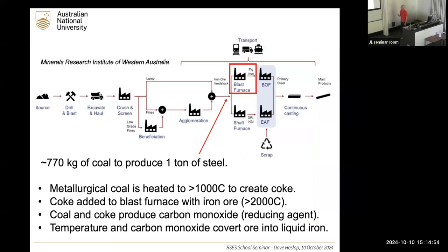So let's look at what's happening in this blast furnace. So, like I said, we've got blast furnace, we're using coking coal to produce pig iron, which then goes into the basic oxygen furnace to remove things like carbon before going into the steel production. So at this stage here in the blast furnace, that's using about 770 kilograms of coal to produce 1 ton of steel. And this is actually metallurgical coal, so that's heated to about 1,000 degrees C to create coke.